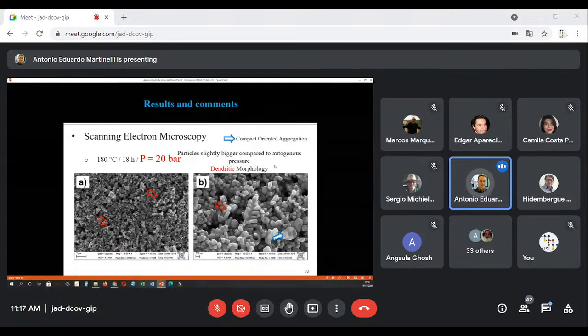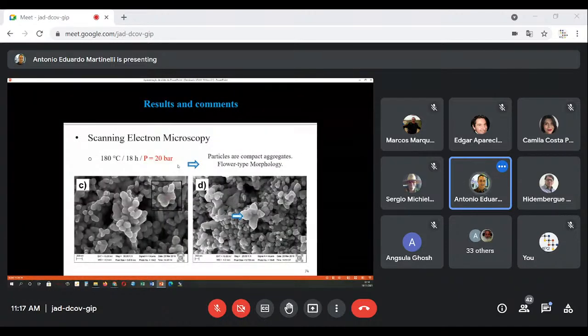Now let's see the effect of pressure. We saw from the X-ray diffraction that pressure does not affect the composition, does not affect phase formation, but affects morphology. So when we increase the pressure to 20 bar, 180 degrees C, 18 hours, what we see is the dendritic morphology. And we continue observing the oriented aggregation, but now the compacted oriented aggregation imposed by the external pressure. At 20 bar, particles are therefore compact aggregates and start to show the flower type morphology.